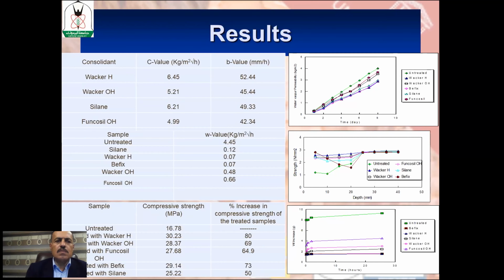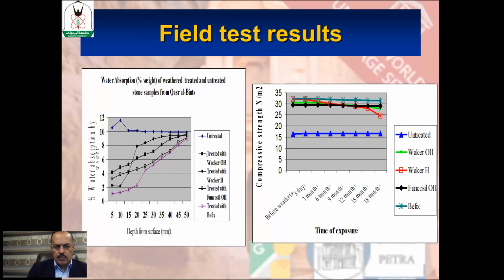enhancement of the stone strength when you compare the untreated stone with the treated one. And also some of these consolidants give really positive results regarding the penetration depth, water vapor permeability, and water absorption. And these laboratory test results were used to design a field testing program to test and evaluate the performance of these consolidants under real environments.